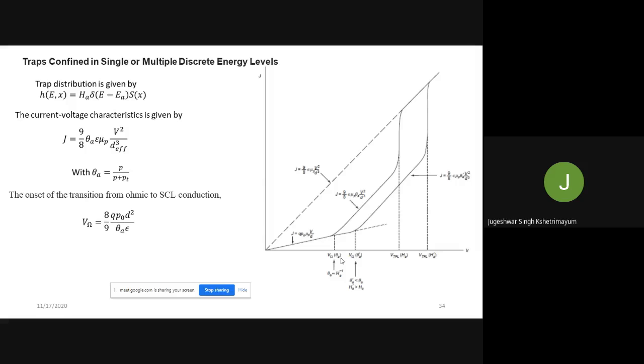The charge transport inside the polymer is controlled by the trapping and detrapping of carriers at both energetic and positional distributions. Traps are nothing but impurities, and they create states in between the conduction and the valence band, between the Fermi level and the conduction band. When the electrons are moving from one site to another, the traps will fill up. Here we see this is the ohmic region, and this is the trapping region. Then there is the Mott-Gurney region. Then the trap is filling up, then another space charge limited region comes here.